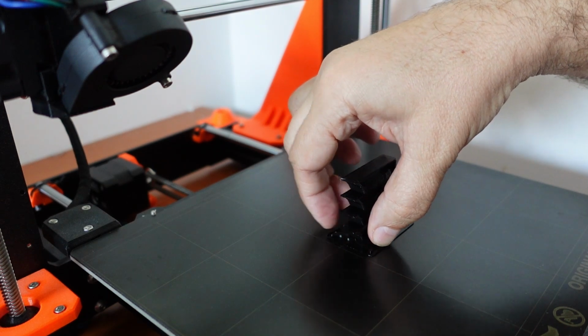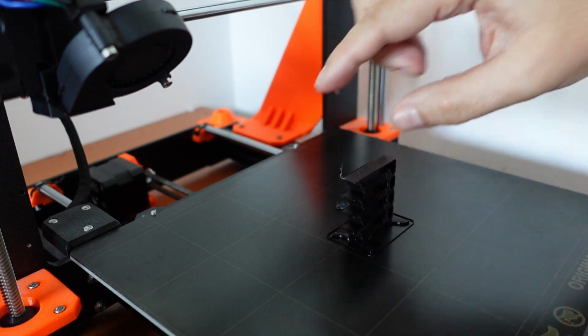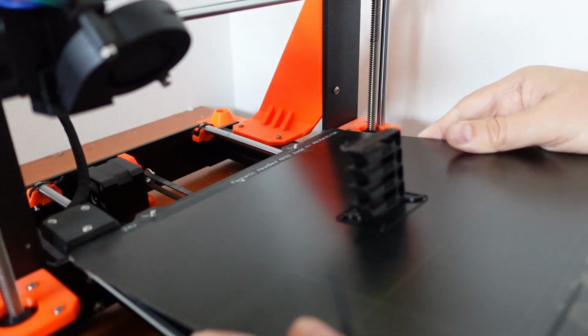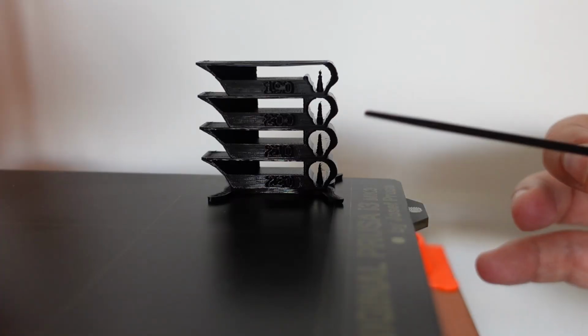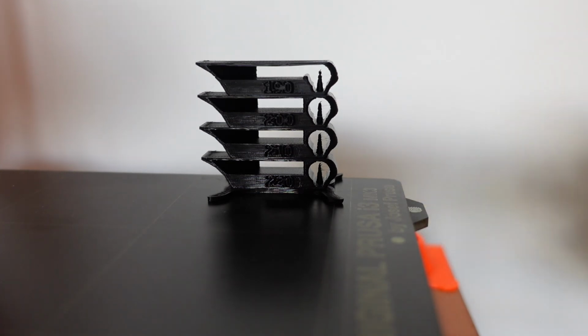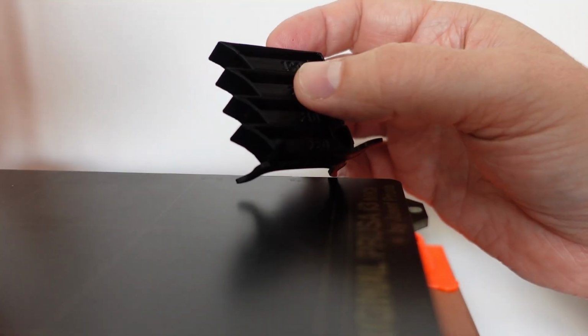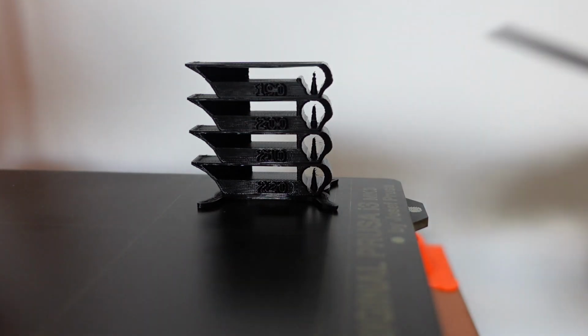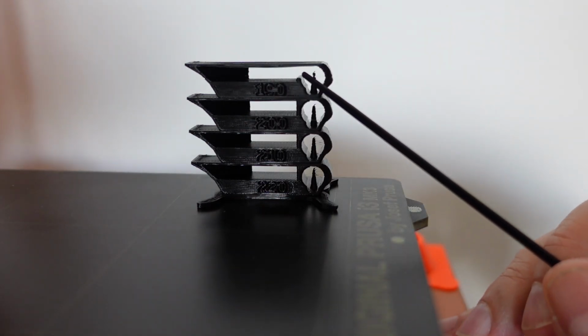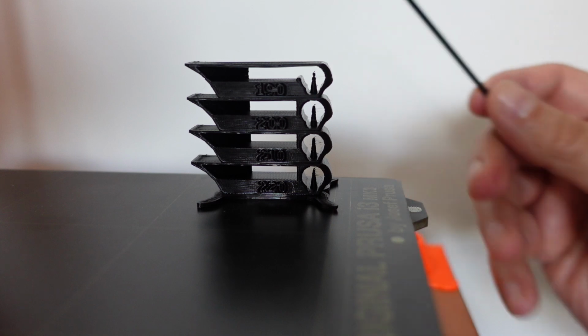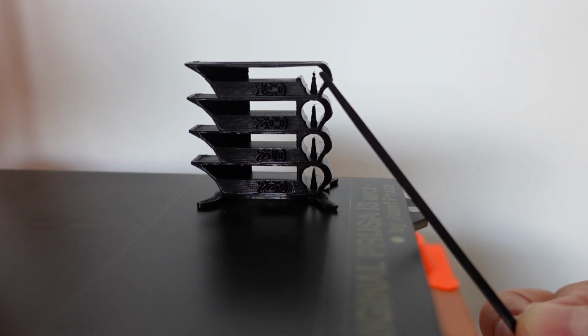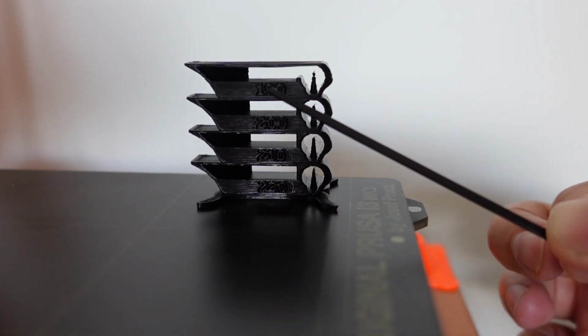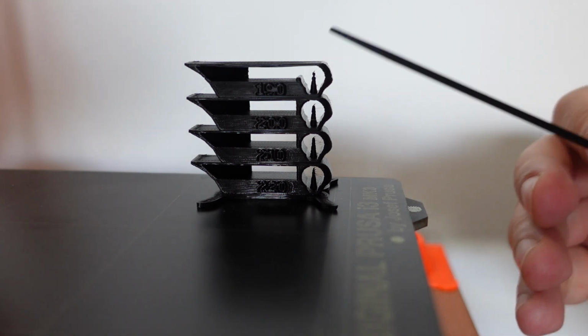Okay, which is great, like regular PLA. And this is the temperature tower. On every element, the overhang and the bridging came out perfectly. The only problem I can see is at 190 degrees, so you can see this wall was not finished, and I can see some under-extrusion here on this candle. So definitely 190 in my case is too low for this filament.